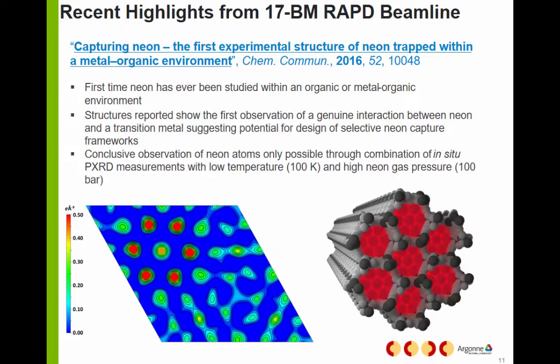Well, we used the same system, and we placed neon in our syringe pump, and we've actually been able for the first time to determine a structure which contains neon atoms within the MOF. We also determined that at low temperature and high pressure, there is interaction between neon atoms and transition metals. This is the Fourier difference map, which shows the position of the neon atoms, and this is the structure of the MOF, and the red represents the position of the neon atoms inside.